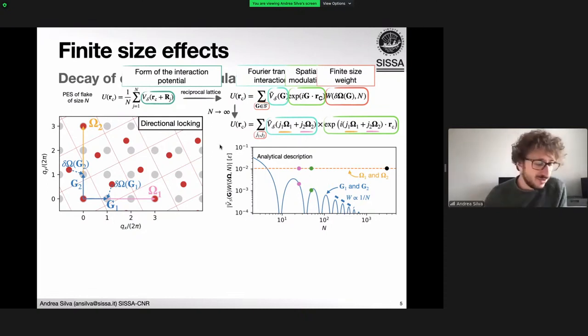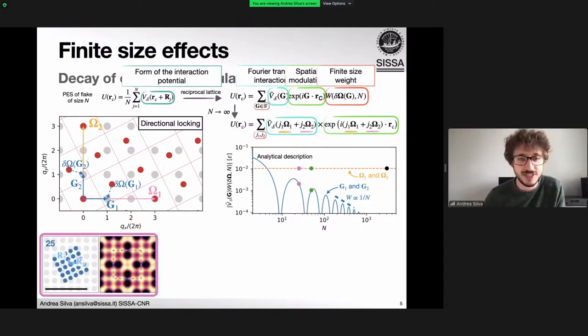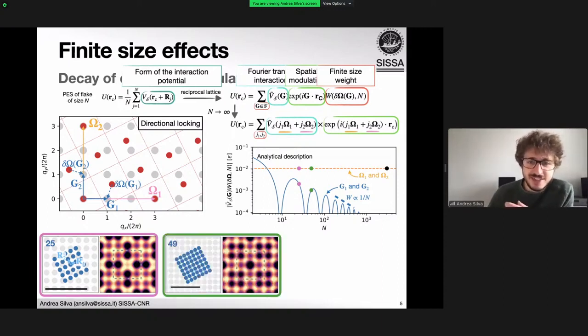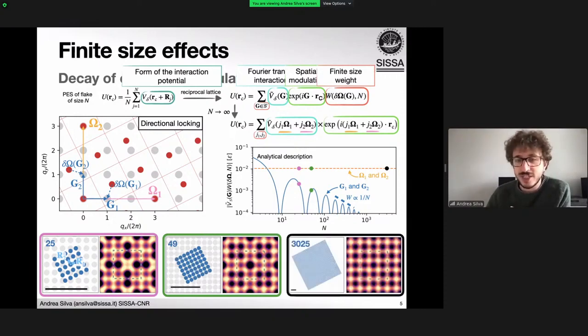So if we take a small flake and we drag it around the substrate, like here, we see that the energy landscape is very complex, and there are many different periodicities and modulations on it. As the size increases and the system realizes its true incommensuration and the other Fourier components decay, we move towards the infinite limit of the interface.